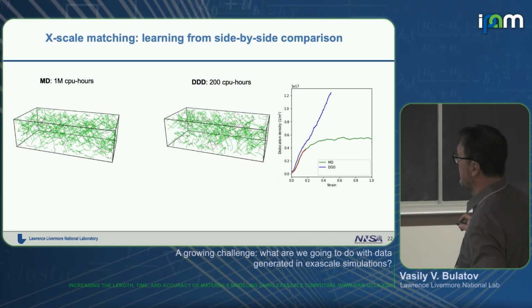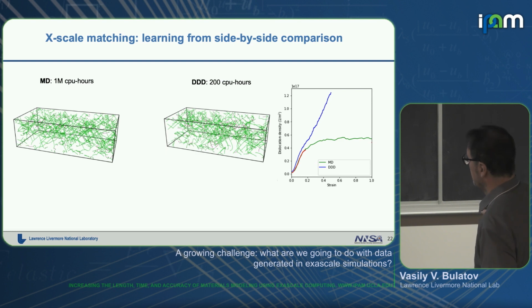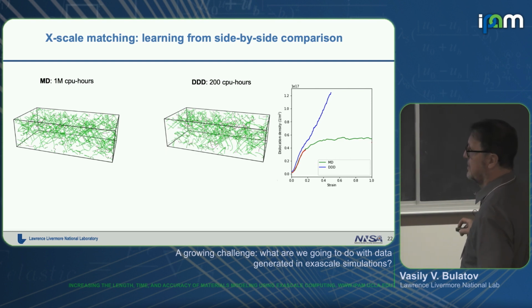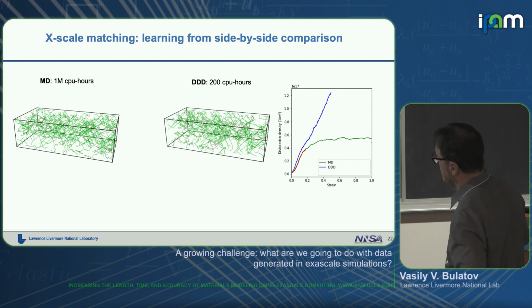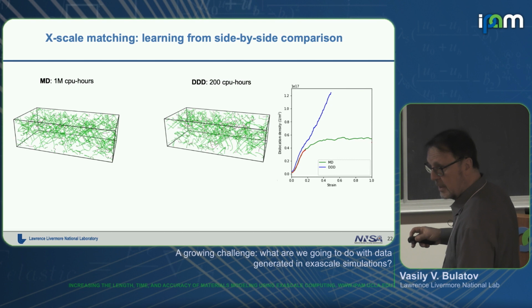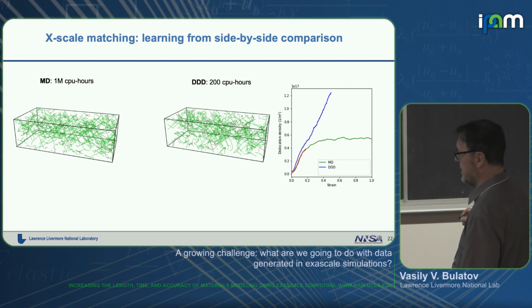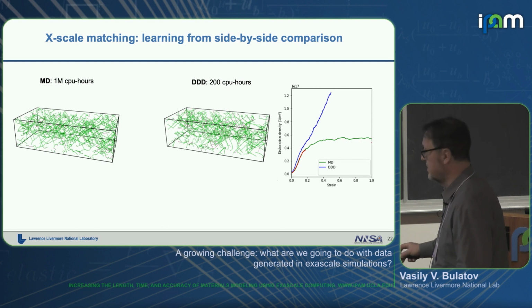They look like they do exactly the same, but they're not really behaving the same way. What is shown here is that when we analyzed how the flow stress behaves in this simulation and that simulation, they're quite different. I'm not showing that. But an even more striking difference was in the accumulation of dislocations. This is what the MD simulation predicts. And as I was showing before, all measures saturate if you're just holding your crystal under the same straining conditions for long enough. And that is what's happening. It's basically steady flow. Dislocation density reaches some steady level. None of that happens in DD. Something is going on, something is different.